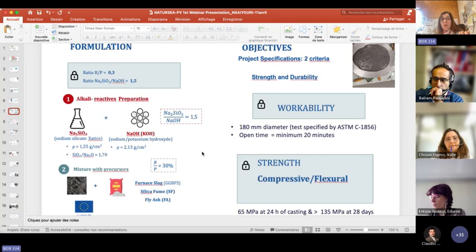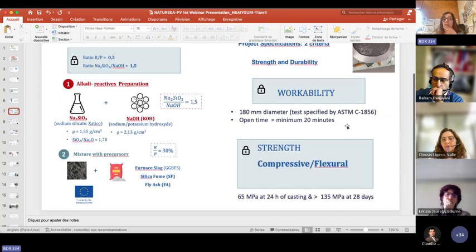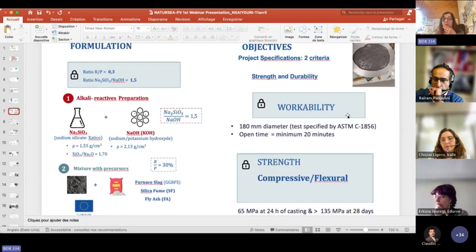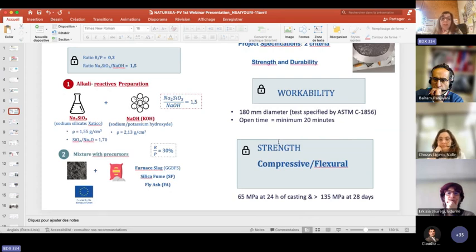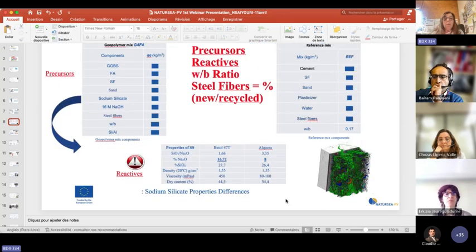Our objectives, or the specification of the project, are about workability and strength, and we need to respect these few points, not more or not less. 18 centimeters diameter for workability. For this, the same test was shown before, and we need an open time of using this mixture of 20 minutes at least. We need also something about compressive strength: 65 at 24 hours and more than 135 megapascal at 28 days.